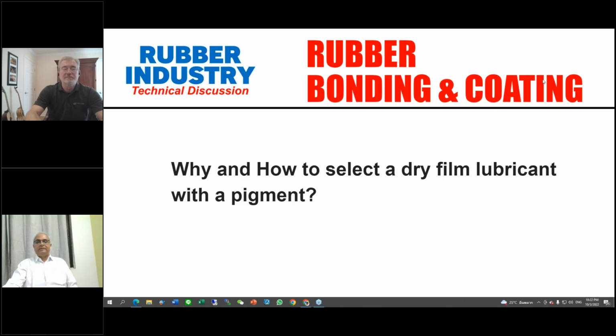The color aesthetics is very important from the application point of view. The formation of the film is helped by the lubricant pigments, and the lubricant pigments separate the mating surfaces that are in relative motion. If you recollect, I had shown you a typical photograph of a coating after application, how it gets mixed up with the surface, the rolling surface part of it, which can guarantee the corrosion and the wear resistance.